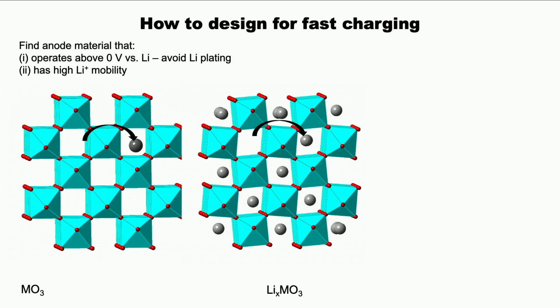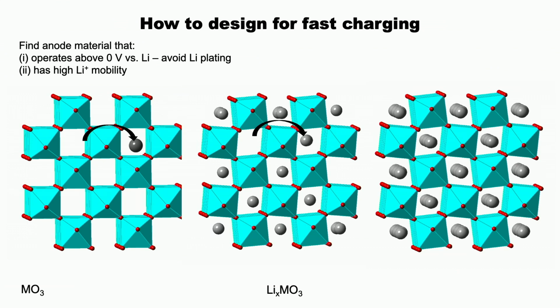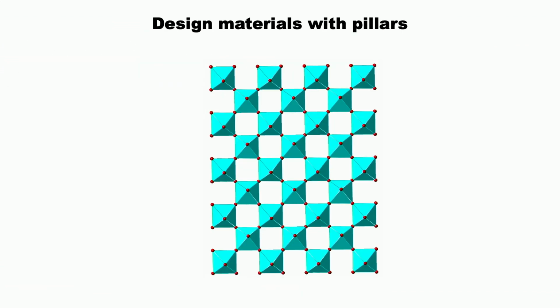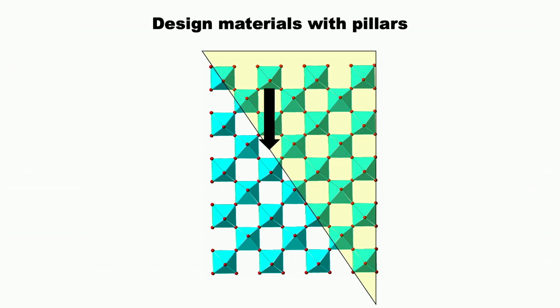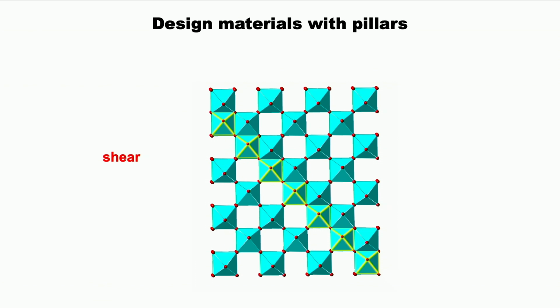And the problem with it is that lithium is too small for most MO3 structures, and so the units rotate and they clamp the lithiums in place. So lithium rhenium oxide is a terrible battery material, even despite its price. So what you can do is to think about how you pillar the structures to prevent those rotations. And so you can take a material and conceptually do a shearing operation. So we fuse the octahedra together, and when you do that and put a lithium inside, you can no longer rotate. So you can just formally imagine that, and it's stuck.